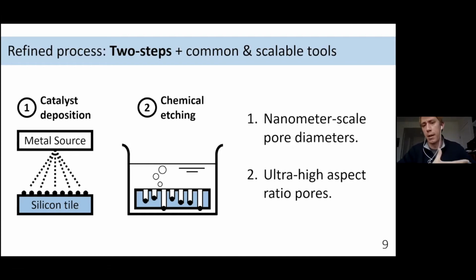The second advantage here is that we can obtain much higher aspect ratios in these nanopores than you could with, say, an RIE approach, where we can get aspect ratios over 2,000 to 1, allowing these very narrow nanopores to penetrate through a very thick silicon wafer, which then becomes our membrane.